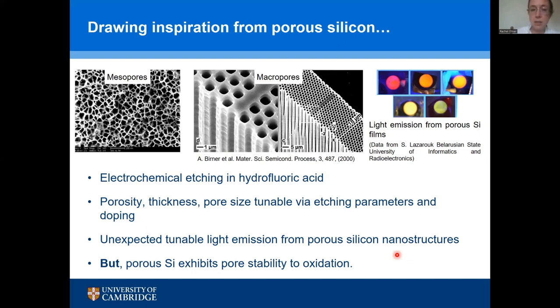So silicon is a material with an indirect band gap, but if you introduce porosity into it, it can become a light emitting material because you can change the way that electrons and holes behave in that material via creating this porous nanostructure. And this sort of porosity that I'm looking at here is often achieved by electrochemical etching, often with hydrofluoric acid. And you can achieve lots of different morphologies by tuning the etching parameters.